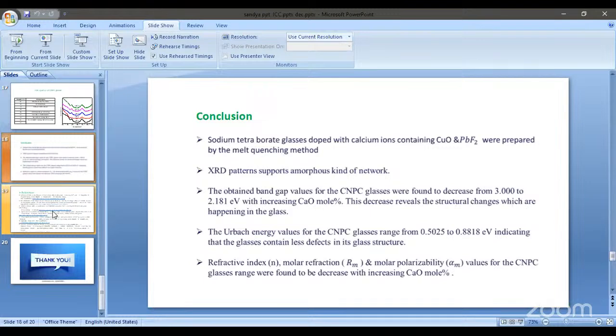And this is the conclusion. Soda tetraborate glasses doped with calcium ions and containing copper oxide and lead fluoride were prepared by the melt quenching method. The XRD patterns give the amorphous nature of the prepared glasses. The band gap values of the CNPC glasses decrease from 3 to 2.181, and this decrease reveals the structural changes happening in the glasses. The Urbach energy values increase, which tells there are fewer defects in the glass structure. And of course the refractive index and molar refraction values decrease with increasing calcium oxide mole percentage.